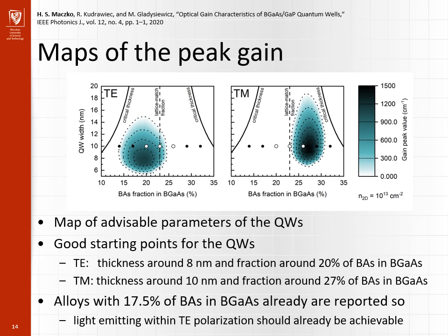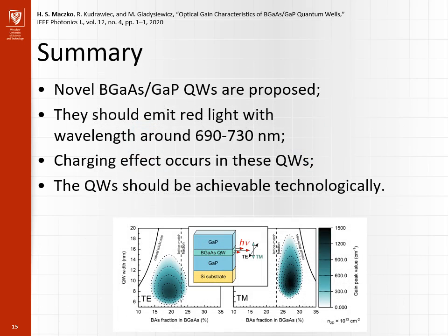The most promising initial parameters of boron gallium arsenide on gallium phosphide quantum wells are found to be 8 and 10 nanometers of thickness and 20 and 27% of boron arsenide fraction for TE and TM polarizations respectively. Structures emitting light of TE polarization should be the easiest to achieve, however higher gain values are found for TM polarization. In conclusion, we proposed a novel quantum well system that can be integrated with silicon technology.